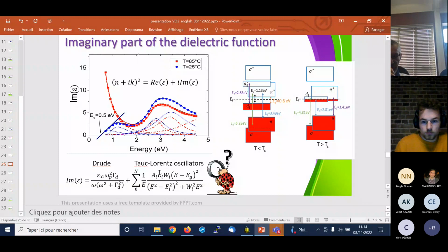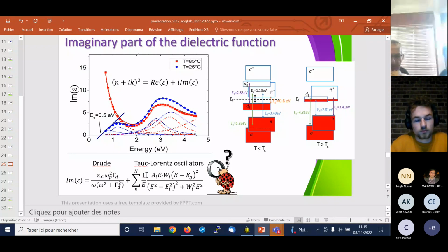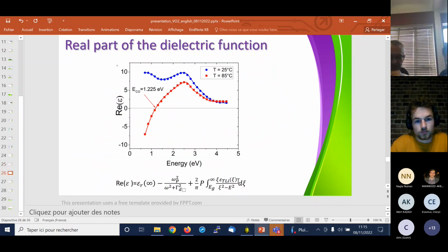And additionally, the Tauc-Lorentz oscillators are very interesting because you see that there is a description of the Tauc-Lorentz oscillator for the imaginary part. And then if you want to calculate the real part, there is an analytical expression for this integral, for the real part. We didn't put it because it's very lengthy, but you can fully calculate the imaginary and the real part, once you have used the Tauc-Lorentz.